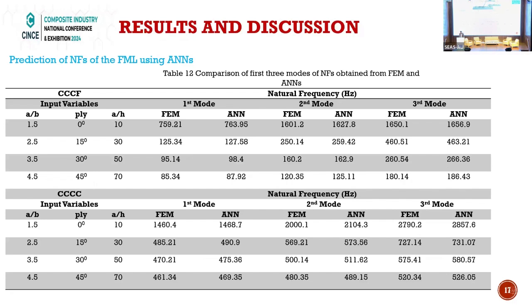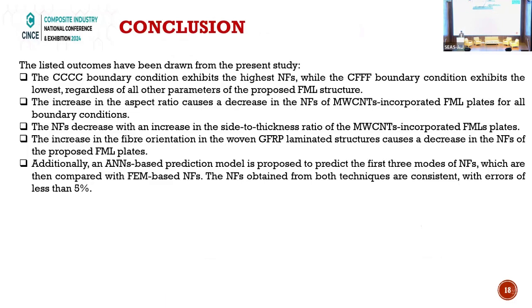Table 12 shows the 3-side clamped boundary condition and all-side clamped boundary condition. So finally, I conclude that for any structure, when we perform modal analysis, the all-side clamped boundary condition has the highest natural frequency compared to the others, because when we increase the constraint, the stiffness increases, which leads to higher natural frequency. Then when we increase the aspect ratio, it decreases the natural frequency. The same trend is followed for side to thickness ratio and the ply orientation angle.